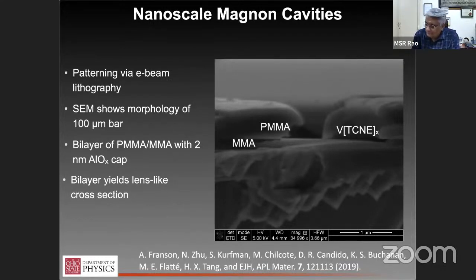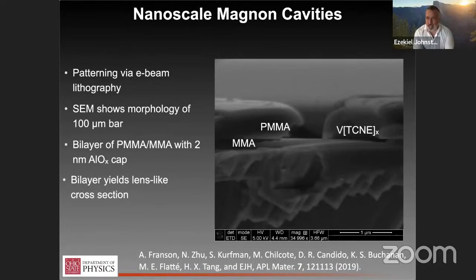Praveen, one question. So this piezo control, do you actually grow V[TCNE]x on PMN-PT? We tried that. I think it might work for single crystal PMN-PT, for flat single crystal. But the transducers that we ended up using that worked best were polycrystalline. This is one of those things, going all the way back to my postdoc, that is still a lesson I need to relearn. These length scales are not tactile length scales, so it's easy to lose track sometimes. The surface roughness of a smooth polycrystalline film is still 50 nanometers. Given our few hundred nanometer film thickness, I think that roughness substantially degraded the film and gave a lot of magnon scattering.